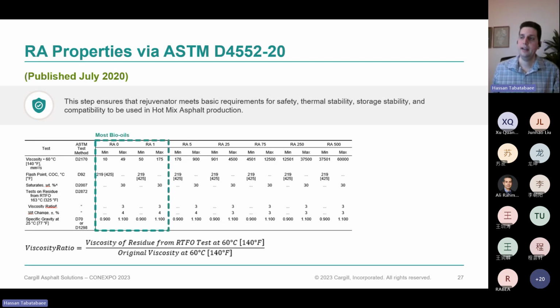In 2020, an RA0 category, the lowest viscosity one, was added to this table to better describe bio-based additives. Generally, since the 80s, the table has had everything from RA1, which means a viscosity of 50 or higher. However, this was found to not be suitable for bio-based additives, which today are actually the most common additive used as a recycling agent in North America and in Western Europe. So the RA0 category was added with lower viscosity without changing the other criteria of RA1.